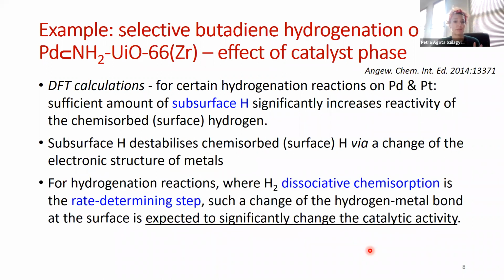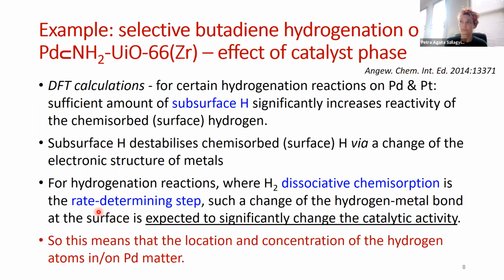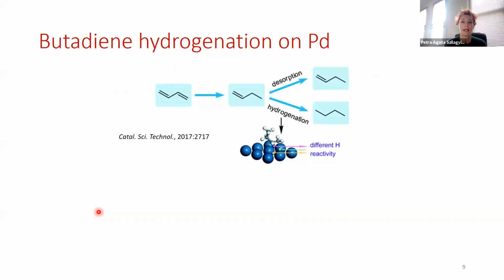And not exclusively, but in particular for reactions where the dissociative chemisorption of hydrogen is the rate determining step, we expect a huge change in the catalytic activity depending on the surface hydrogen concentration. So what that means is that the location and the concentration of hydrogen atoms in or on palladium actually matter a lot. We looked at this reaction. This is the selective hydrogenation of butadiene on palladium. So this is a well-known reaction.